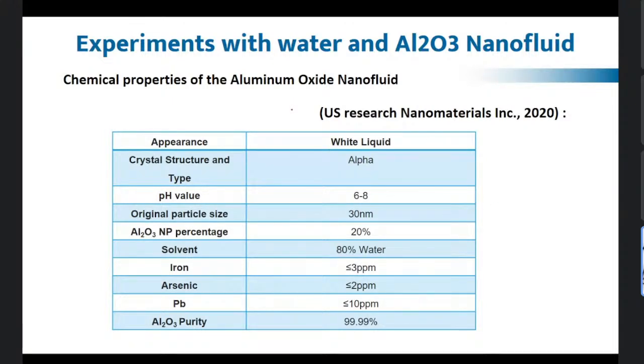The nanoparticles that we used for our experiment were aluminum oxide, and we mixed them with water. So we obtained a 20% concentration of aluminum oxide particles in water, and then we diluted it for our experiments as per our plant scheme.